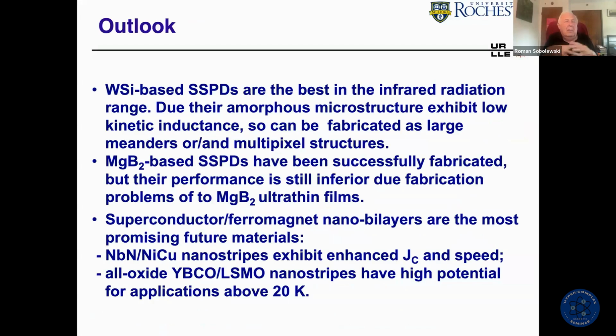At the moment, most of the community is happy with niobium nitride or tungsten silicide detectors working at helium temperature in cryocoolers because they are commercially available, very reliable, and not that expensive. Research has started to move into higher temperature materials like magnesium diboride. Remember, that has a 40 Kelvin critical temperature. Successful devices were fabricated, but they're not as good because the development of magnesium diboride, the quality of films, which need to be extremely thin, is far behind conventional metallic superconductors.